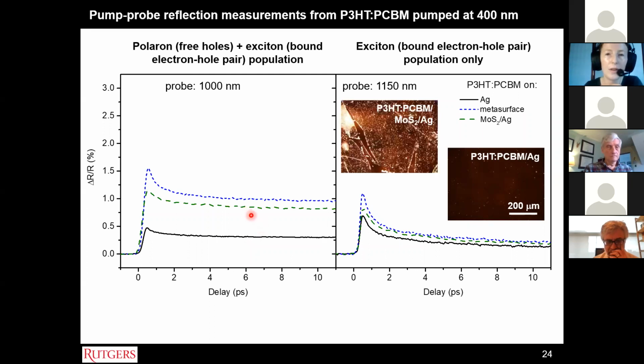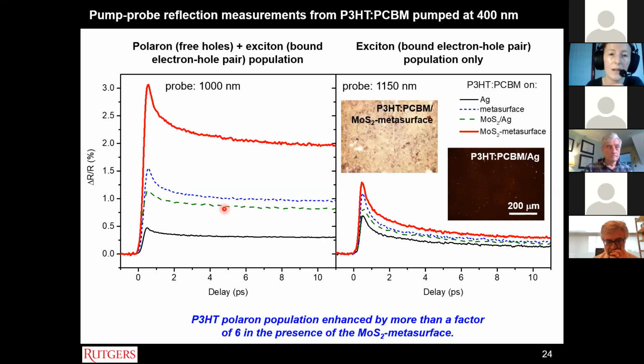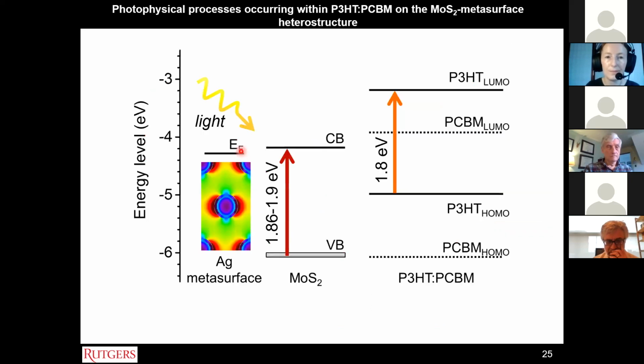Okay, so for the addition of the MoS2 on planar silver, there's actually an improvement as well on the polaron population, and that's without the metasurface. And then combining the two, we get a very significant improvement in the polaron population by more than a factor of 6 in the presence of the MoS2 on the metasurface.